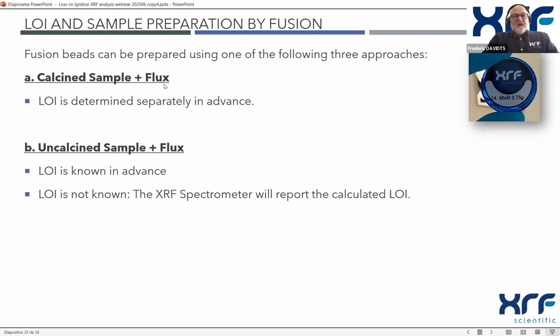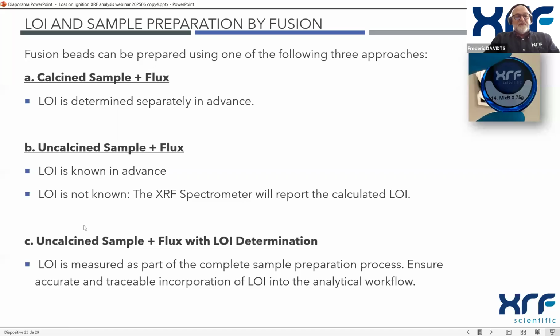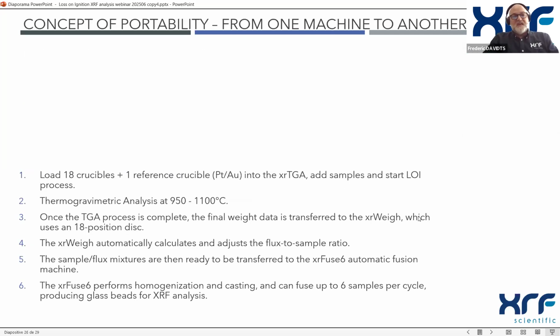Now, if we come back to the way we can present the sample for the fusion, we can start with the calcined or the uncalcined sample, but there is a third option using the uncalcined sample. But in this case, the LOI is measured as part of the complete sample preparation process. And as you will see, it has a great advantage in the workflow and surely for the accuracy. So in that case, we will again load the crucible.